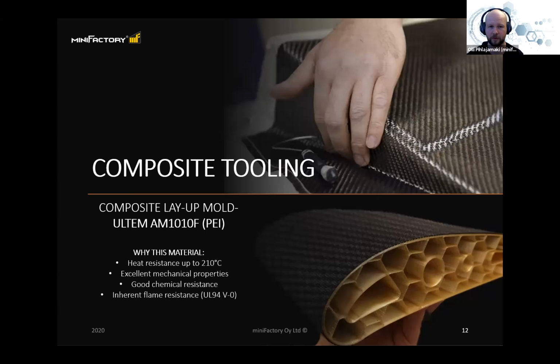So this material can replace metal in layup molds, and the material can be packed for vacuum and baked in the temperatures, or cured in temperatures, that are required to make composite parts. So it's a really interesting application for this polymer, which makes composite molding really cost effective with this technology.